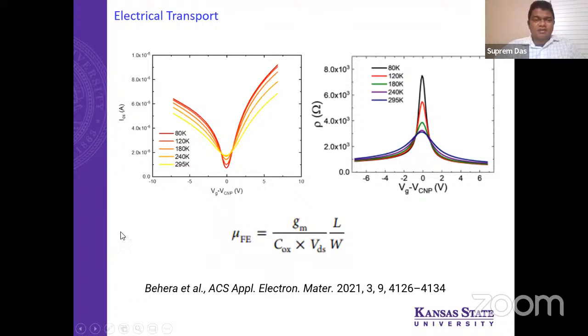So now looking at the transport, if you look at the transistor characteristics, actually it's a very nice ambipolar. As I was saying before, this is your hole transport, this is your electron transport. So both electrons and holes you can generate depending on how you are controlling the electric field. Now we also did temperature dependence of this transport or conductivity. You can see a very nice variation of this conductivity in the hole region, the electron region, and also near the Dirac point. And if you extract the resistivity, you can see very nicely the resistivity is changing from p-type to n-type through the Dirac point.